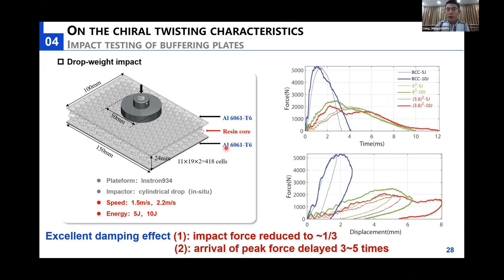Lastly, we also carried out a drop impact test on different sandwich structures cored by different lattice structures. We have adopted two kinds of hyperbolic lattice and a BCC lattice core. The force-time diagram revealed that an excellent buffering effect has been achieved since this impact force is about one-third for this hyperbolic lattice structure, and the arrival of this peak force is delayed to more than three times.